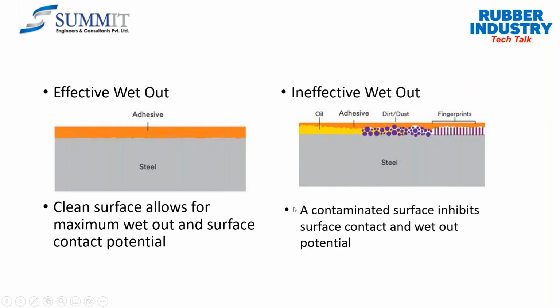whereas if there is ineffective wet out, or any dirt or dust is available, then that is not allowing you to have the effective adhesive. And this contaminated surface inhibits the surface contact and the wet out potential, which is creating the problem for you. One more aspect of this is the surface energy, especially for the rubbers. Normally rubbers or engineering plastics have a lesser surface energy. So by adopting the cleaning process, we are able to increase that surface energy also.